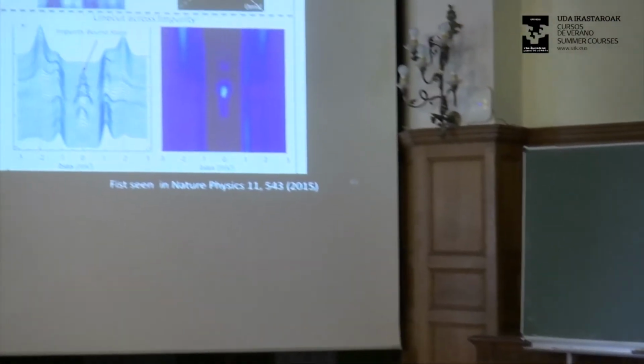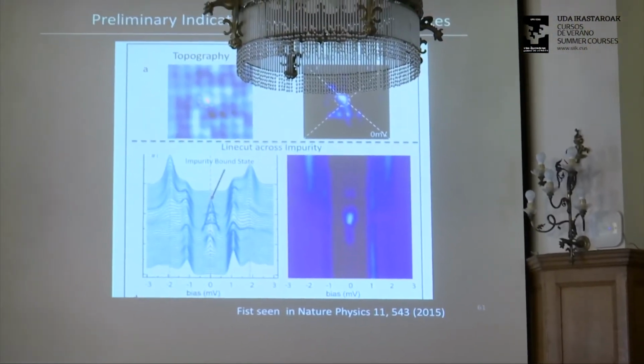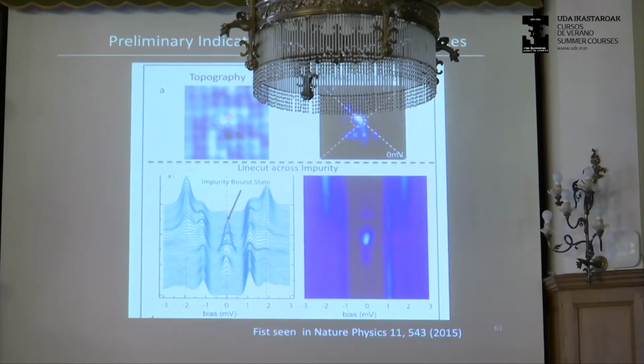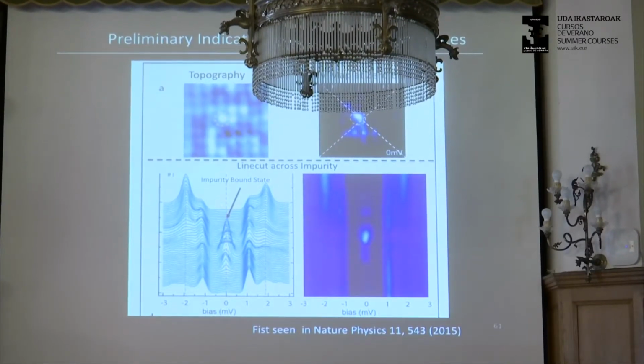So here is an impurity bound state. Here is an excess ion, right? And interestingly, if you go on top of it, you get this beautiful zero bias peak, okay? And this already tells you that there's something very interesting happening in this compound, right? The peak is really centered at 0.